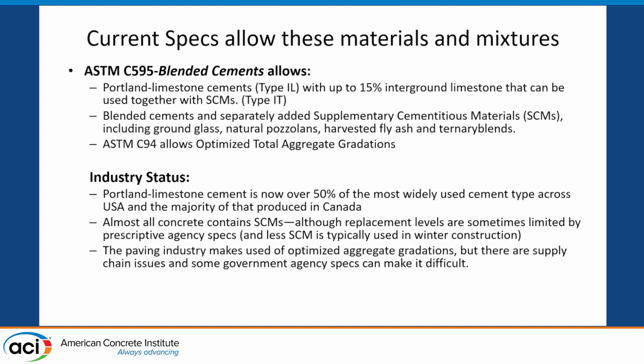For example, C595, the blended cement spec, that's where the type 1L cements ended up. There's also a type 1T, which is limestone plus an SCM, such as fly ash or slag, which allows you to blend these materials. And as I said, C94 allows optimized aggregate gradations. Last month, apparently, Portland limestone cement is now 54% of U.S. production of cement type. And right now, like I say, in certain Ontario, I can't speak for the whole of Canada, it's 100%.